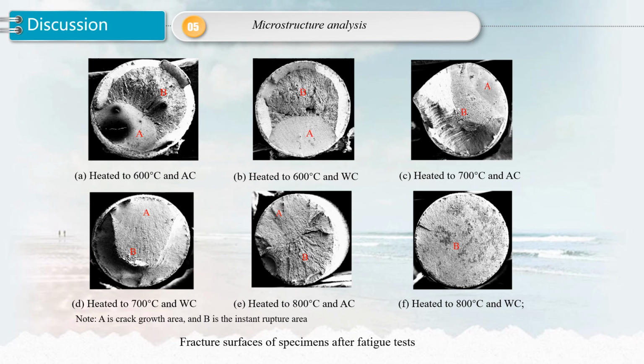To make a comprehensive understanding of the fracture mechanism, the fractured sections of specimens after fatigue tests were observed by scanning electron microscope, as shown in the figure. As seen from the image, the fracture surface can be divided into two parts. The first is the so-called crack growth area, where the fatigue crack initiates and propagates. It is smooth with a honeycomb shape, as shown in picture A.